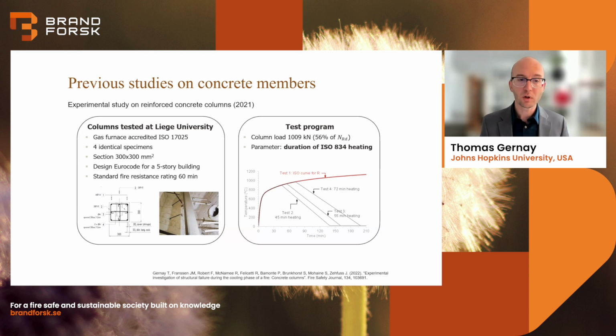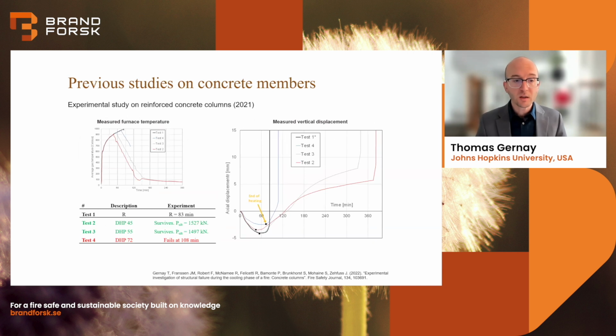So here, 4 columns were tested at Liège University in Belgium. And you can see column number 1 was tested under the standard fire resistance testing protocol. And then in test 2, the column was heated for 45 minutes, followed by cooling. Test 3, 55 minutes, and test 4, 72 minutes. The results are shown here. So the first test allows establishing the fire resistance time at 83 minutes for this column specimen. So R is equal to 83 minutes.